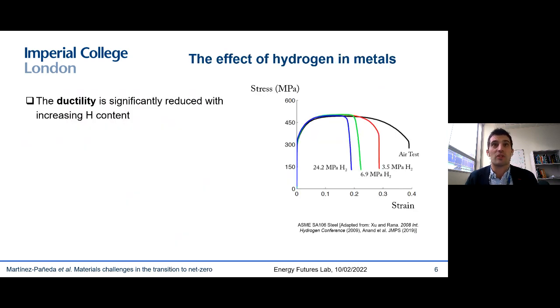One of the effects that you will see when you expose metallic samples to hydrogen is a significant loss in ductility. What you see here are uniaxial stress-strain curves. So I just expose my samples to hydrogen, for example, to hydrogen gas, and then I pull, and then I see this stress-strain behavior. And you can see that as you increase the hydrogen content by, for example, increasing the hydrogen pressure, there's a very significant reduction in the failure strain.